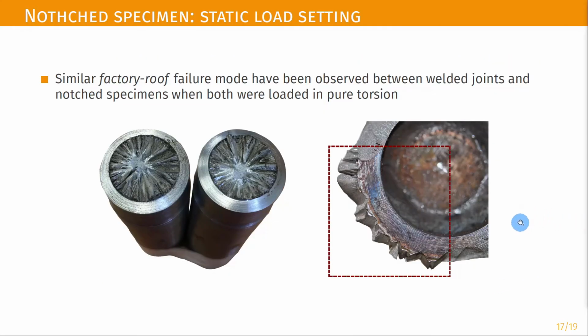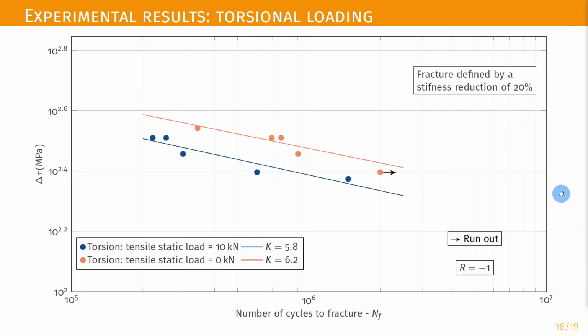In these figures is visible a comparison of the failure surfaces for the notch specimen and the welded joint, both loaded in pure torsion. We can distinguish clearly the classic factory roof type fracture mode. Nominal shear stresses as a function of the number of cycles to failure is given in this slide. For this specific case, the end of the fatigue test has been imposed for a stiffness reduction of 20%. As expected, although the preload is quite low, this has worsened the fatigue life of the component, in a similar way as observed for a welded joint.